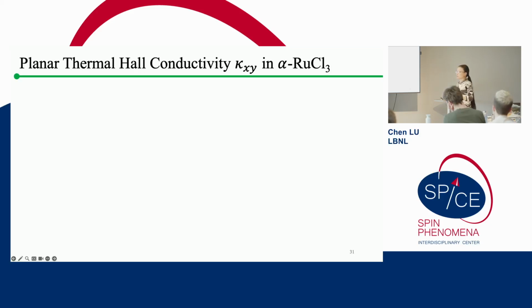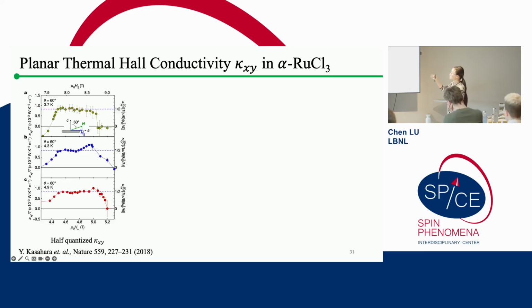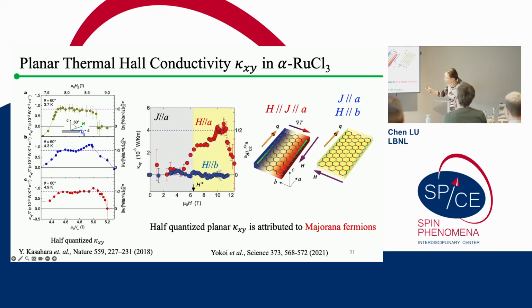At this point, you probably want to ask me, why do you do a thermal Hall effect measurement in such a weird way, in a non-conventional Hall effect configuration? The answer is here. The very first planar thermal Hall effect study was also done in this so-called alpha ruthenium trichloride. I think I already showed you this figure in the previous introduction part. Basically, for the half-quantized thermal Hall conductivity reported by Professor Matsuda's group, the very first experiment later on was done, as you can see from the configuration, with a tilted field, which means the magnetic field had both an out-of-plane component and an in-plane component.